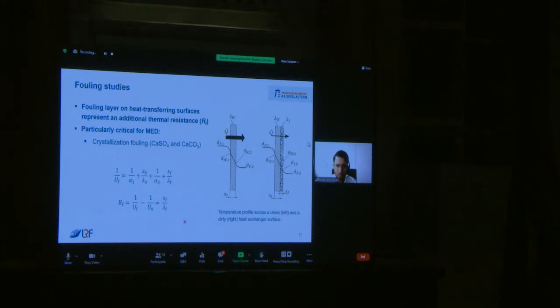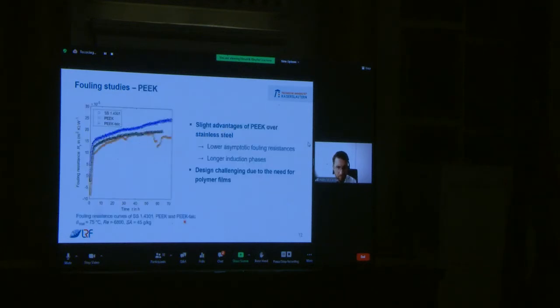For the artificial seawater test system, the components calcium sulfate and calcium carbonate are mainly relevant for the fouling processes, and we have determined the fouling resistance experimentally for PEEK and the polymer composites. Here at first for PEEK, pictured are the fouling resistances versus time for stainless steel PEEK and talcum-filled PEEK. Overall, the differences are not very large, but we see slight advantages for PEEK, especially regarding the asymptotic fouling resistance. Also interesting is this drop in the fouling resistance, which I will discuss in more detail later.